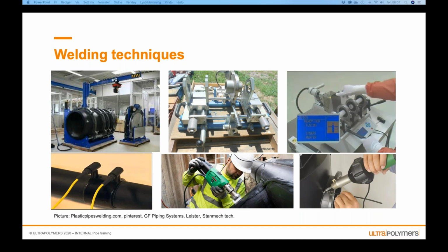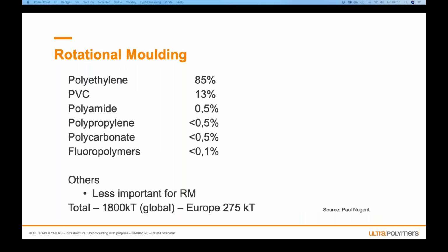So if you go back to rotomolding, polyethylene is dominating in rotomolding, as you know. According to Paul, more than 85% in the world are using polyethylene. There are still some PVC production, but not so much. He says that the global volume is 1,800 kilotons, but I think we can double or triple that number at least. In Europe, it's approximately 275 kilotons going into rotomoulding, and it's mainly polyethylene. The polyethylene number in Europe is probably more like 95%.